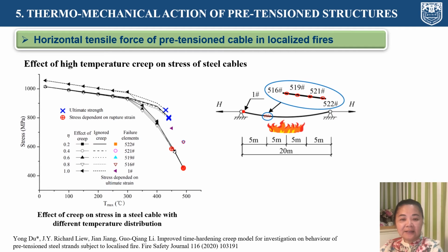Numerical analysis using ANSYS software discovered that the steel cable would fail when rupture strength is achieved at elevated temperature, when the high temperature creep strain was considered. It is worth noting that the ultimate strength of cables would not be achieved at elevated temperature, since the creep strain enhanced the reactions of cables. Thus, when the total strain of steel cables increased dramatically due to the increase of creep strain after 300 degrees, the tensile force decreased more greatly than the ultimate strength in cables at elevated temperature.